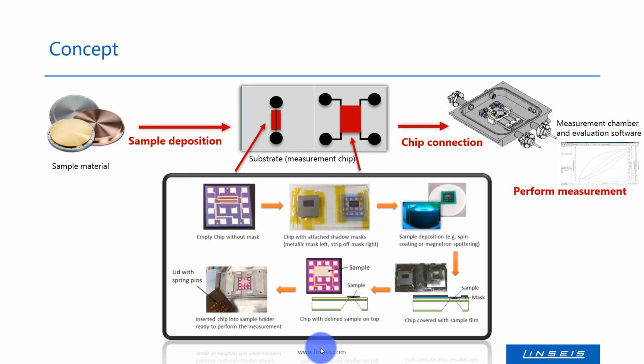The deposition routine depends on the conditions, of course, but is designed to be rather easy. We use kind of masks for protecting the connecting parts of the chips during the deposition. After the sample is deposited on the entire front side, we remove the mask and have the residual sample in the designated areas only.